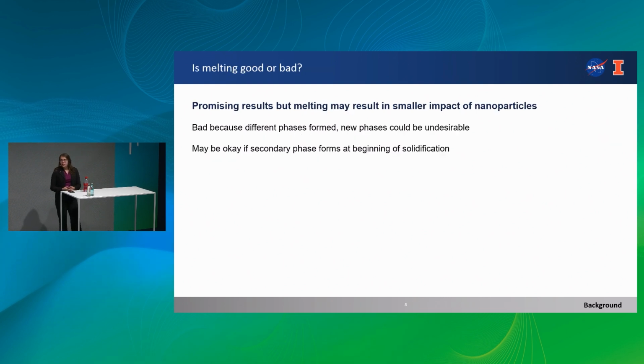But thus far, this question of is melting good or bad? Well, there's a lot of promising results on the impact of nanoparticles, but the results can kind of vary. If you get new phases that form these cellular structures and form brittle compounds along the grain boundaries, this could potentially be bad. But if you get a secondary phase forming at the beginning of your solidification process, then these nanoparticles can actually still continue to act as nucleation sites and be really helpful.